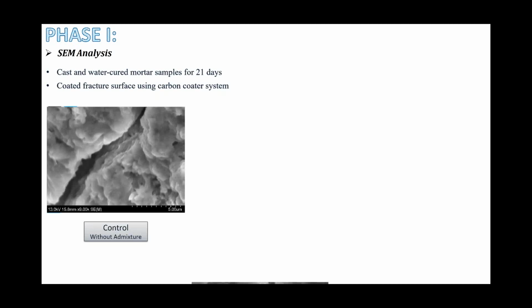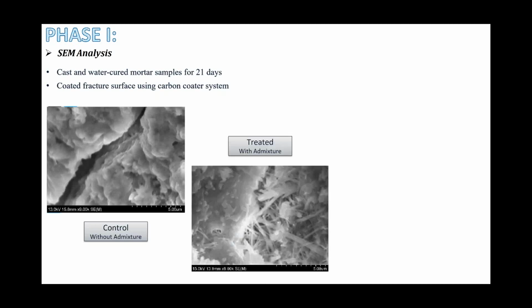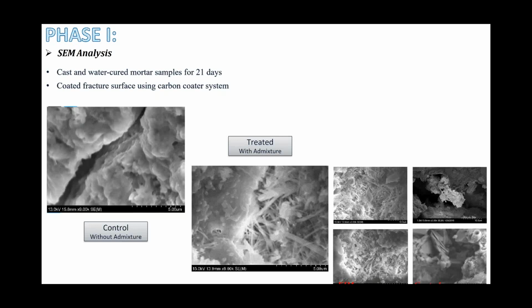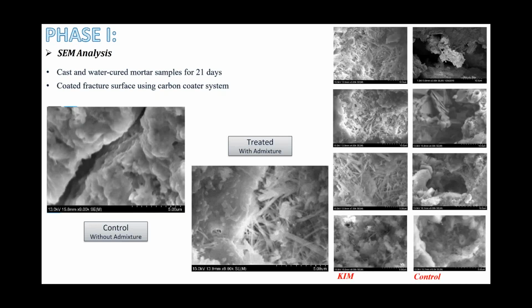As you can see in the photo, there's a crack inside. I also cast samples where you can see the crystal growth inside the cracks, which gives us an indication that this admixture performs best in crack healing. Here I put some photos so you can compare the control samples without admixture and the ones with admixture. On the left-hand side you can see the crystal growth inside, and those crystals eventually act as a membrane which blocks the water pathway inside the concrete and makes the concrete heal better.